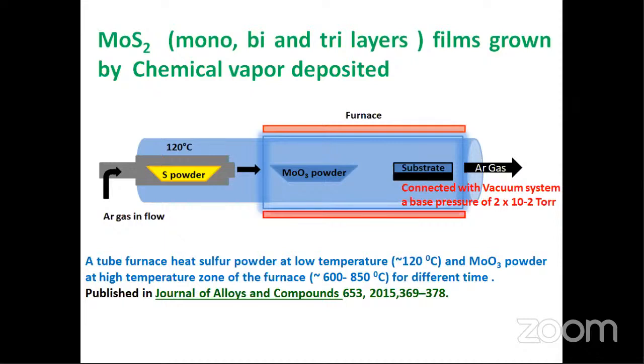First, we synthesize the MoS2 materials in the presence of sulfur powder, with the help of temperature and the flow of argon. The argon flow we kept fixed during the whole experiment, nearly 100 sccm, and we only vary the amount of sulfur and the amount of the MoO3 precursor, as well as the temperature of the high zone furnace. The low zone sulfur temperature we are not changing. We put the same sulfur powder in the low temperature zone, at 120 degrees centigrade.